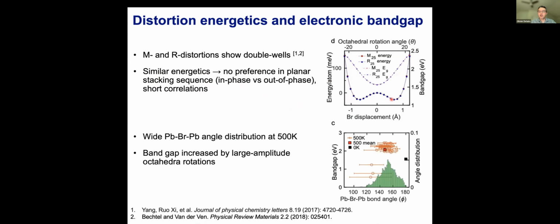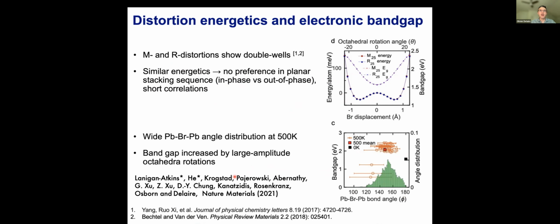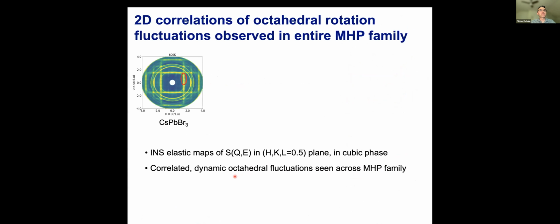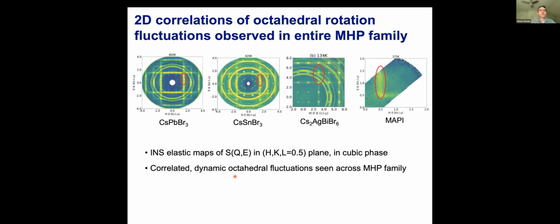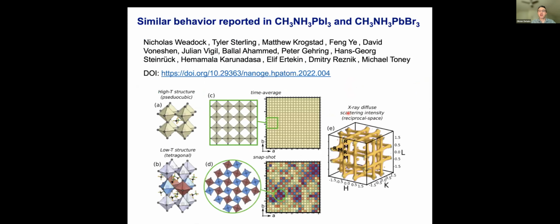We can go further than these types of potential energy calculations and do full MD simulations. I'll show you also some more recent work where we do a lot of machine learning MD simulations, which is going to be very useful to further investigate the stronger anharmonic materials. So I mentioned we see this type of behavior in the entire family of the halide perovskites. This is some unpublished work here that shows this. So I'll focus next on the double perovskite system, which is lead-free. So this effect is not necessarily associated with having lead ions, as is sometimes claimed. And we also see it in hybrid systems, and that's, by the way, also reported by other groups now.